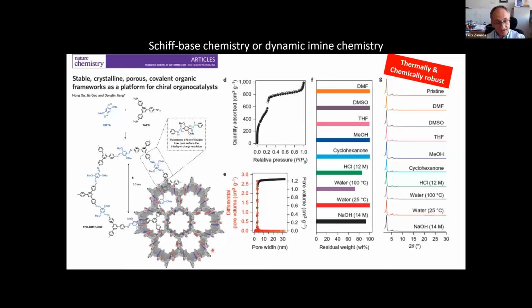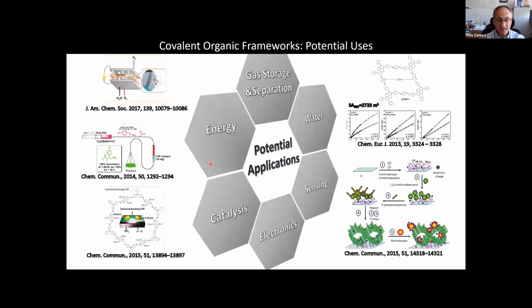Okay, so at the end of the day, you get this nice structure, and as you can see here, we have nice porosity and well-defined pore sizes. But even more importantly, this material is chemically robust. When you immerse the material in water, or even boiling water, or under strong acidic or basic conditions, or this long list of organic solvents, the material retains the crystallinity and the porosity. So it's not only thermally robust, but also chemically robust. So now we can think of properties and potential applications for these new materials. Applications, for instance, in energy, water decontamination, contaminant detection, sensing, electronics, catalysis, or gas storage and separation.